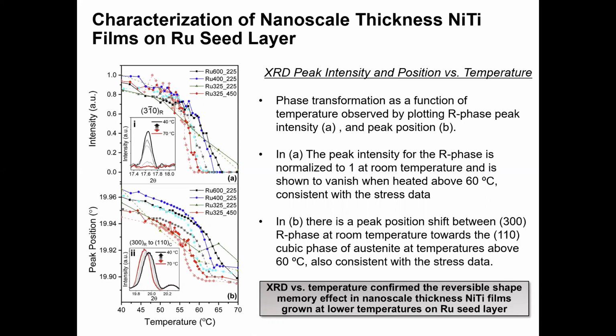In B, there's a peak position shift between the 300 R phase at room temperature towards the 110 cubic phase of austenite at temperatures above 60 degrees. And this is also consistent with the stress data, directly confirming the transformation between austenite and R phase in each of these films, including the films deposited at these relatively low temperatures of 325 degrees.